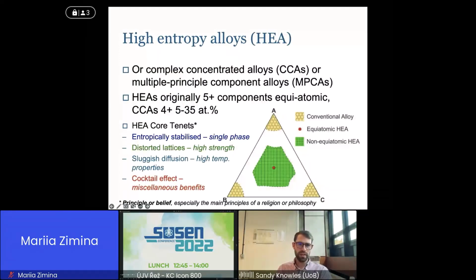So in high entropy alloys, there was this idea that it's because you're mixing lots of elements together that you're gaining an entropy, and hence the name. So maybe you get entropic stabilization. And there's a number of other benefits that seem to be coming out of this, particularly towards high temperature strength and slow diffusion. And one of the ones that catches a lot of my interest is that quite a number of high entropy alloys are showing very good irradiation damage tolerance, potentially much better than conventional materials. So that's a very interesting concept for us to understand and also to exploit.